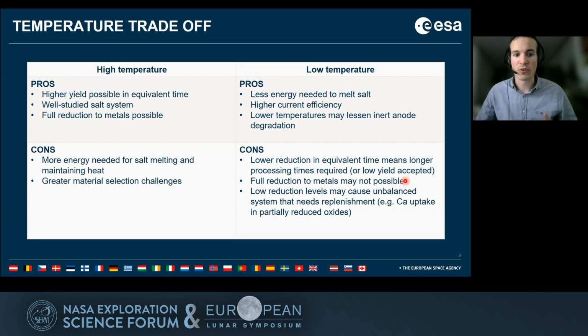Also with a lower reduction, if we don't have a full reduction, the calcium also plays a role, as it can form intermediates during the reduction process. And then if you partially reduce your oxide, the calcium is still in your structure. So over time, if you take out your regolith, you lose a bit of calcium. We have to understand this because, of course, we don't want any consumable in the system. Otherwise, we lose a strong asset of using this system.